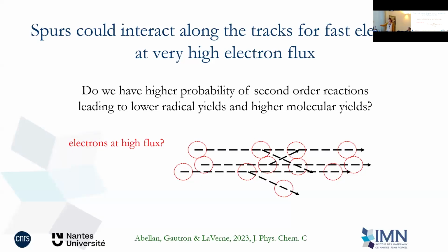So the whole point of this paper was also to say that the G values we are using for models, because of these faster, earlier stages, are probably different from what we think, probably not right. So we shouldn't take them directly from radiation chemistry, we should revisit them. Okay, thank you. But right now we are in the non-homogeneous regime, like in this slide.